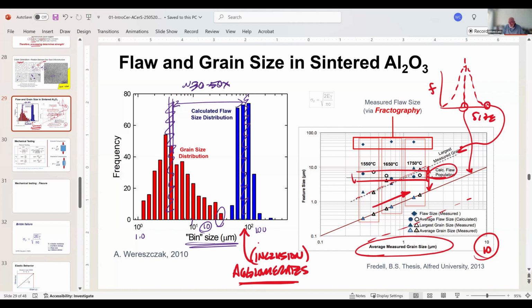When they did fractography on the samples, these were the flaws that they found. So notice that the calculated flaw size distribution and the measured from fractography is a huge difference, but this measured flaw from fractography also is constant, independent of the temperature that was done, independent of the average measured grain size. And so this is telling me that these are the defects that are in the system. Now, why is my calculated flaw population different than my measured from fractography? We'll get into that to a certain extent.